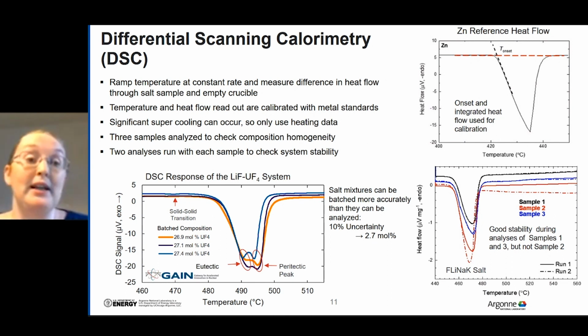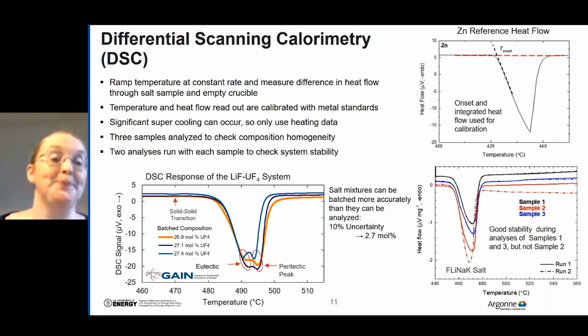We also only ever use heating data for our phase transition temperatures because we've observed significant supercooling with molten salts. So that's another quality affecting tip. We also try to use 3 samples to verify that the salt batch that we're looking at is homogeneous. And every sample is run at least twice to check system stability.